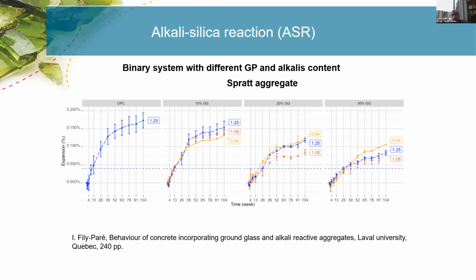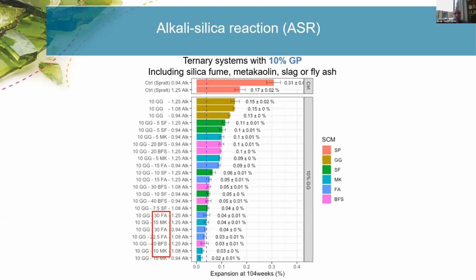But it is important to say that even if it's decreasing, there is not really mitigation. So the mitigation is not really happening unless you go to ternary blend. So at the binary blend, at this ratio that we worked with, it's very difficult to say that it is mitigating. Of course, I speak in the glass powders about the high alkali glass powder, not the low alkali.